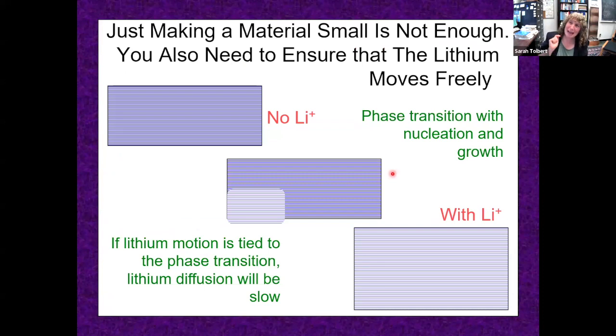It turns out, however, that it is not enough to just make a material small. You also need to make sure that the lithium can move freely through the network. And the problem is the crystal structure. So pretend these lines are lines of atoms. The crystal structure without lithium and with lithium is generally not the same. And so to stuff in lithium, you have to create a little domain called a critical nucleus of the new phase. And then this domain has to propagate or grow through the material. And if lithium insertion is tied to this phase transition, it's unfortunately going to be slow.